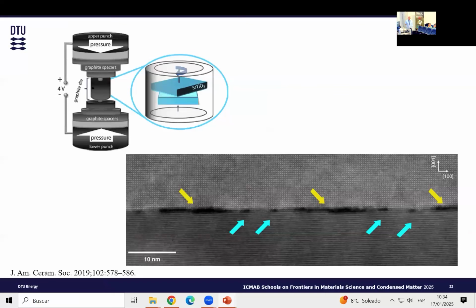This is a work which was already published in 2019. It is two single crystal strontium titanate, and they put them together. They put a pressure of about 1.2, I think, gigapascal. They heat it up to about 1,200 degrees, and then rotate them relative to each other. And what they see is something that we have observed.